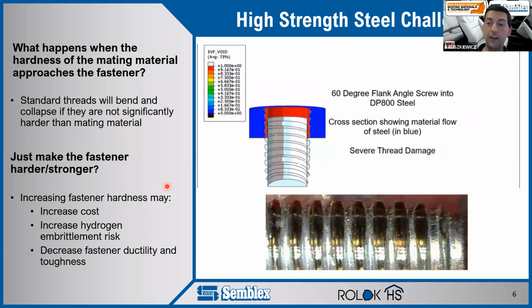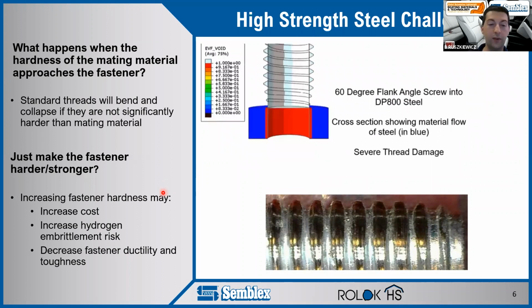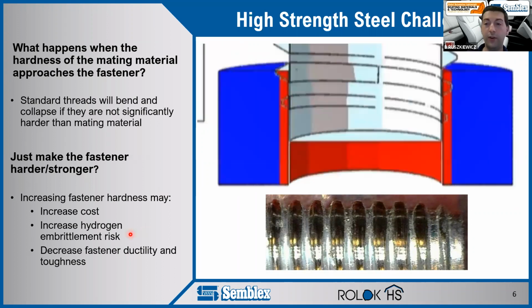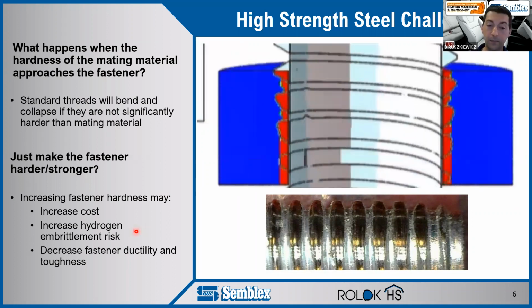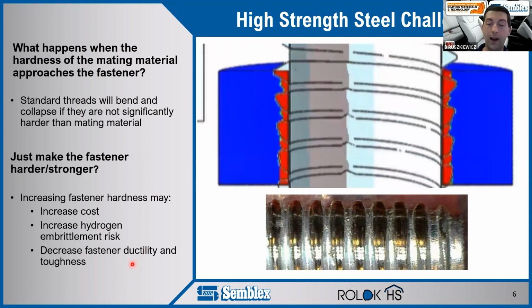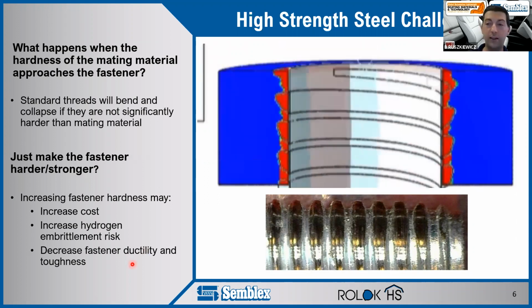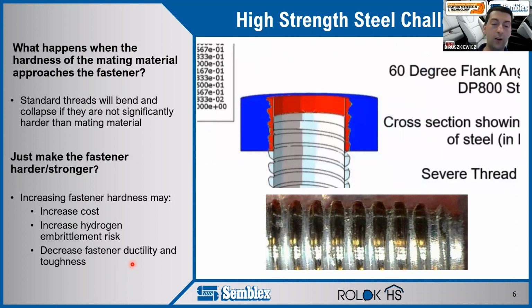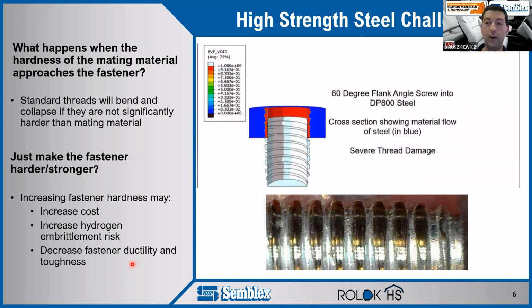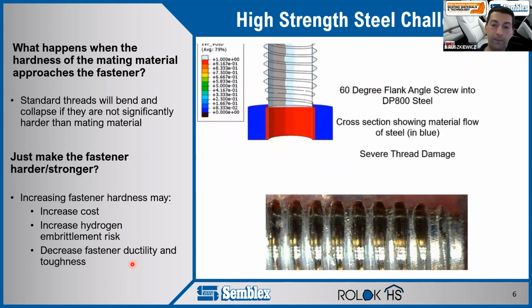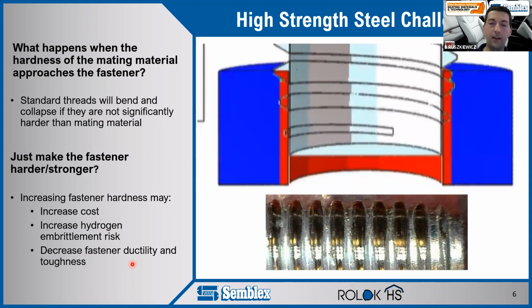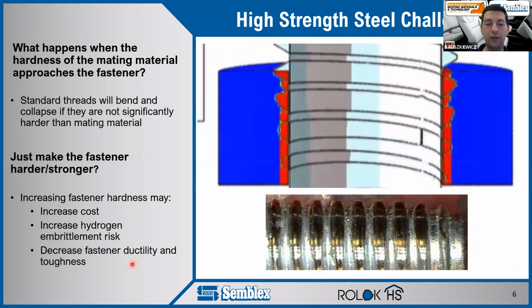In addition, when you get into these harder, higher strength fasteners, you tend to have an increased risk for hydrogen embrittlement, especially if you're going to use an electroplating with it. And then finally, the higher strength fasteners tend to have less ductility and less fracture toughness, which can be an issue if it's a safety critical application, especially if it's a seat bolt and that really can't fail in a crash scenario.